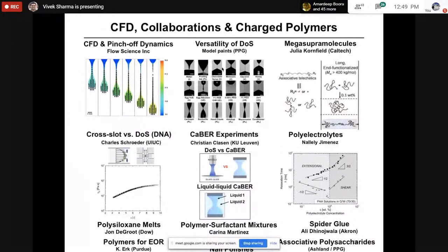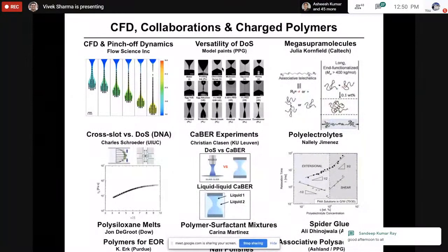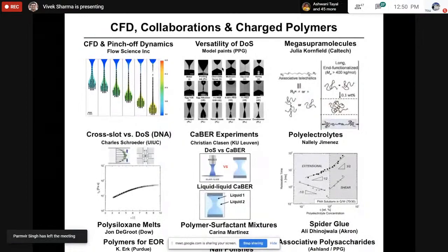However, between water and glycerol or water and honey, the difference is stark, because one gives you inertia capillary thinning and the other gives you viscocapillary thinning. For glycerol, honey, molasses, or glycerol-water combinations, if you know the surface tension, you can map out the viscosity, even the shear viscosity, because for Newtonian fluids the extensional viscosity is just 3 times the shear viscosity. The bigger difference arises in viscoelastic or power law fluids, where shear viscosity is not the only thing that affects things; it is the actual extensional viscosity, and all of that is correlated with what happens to the microstructure.